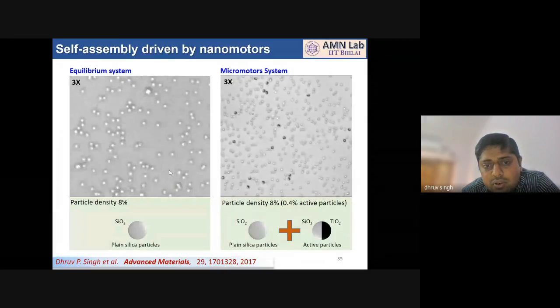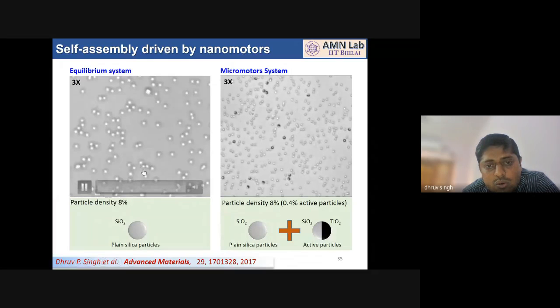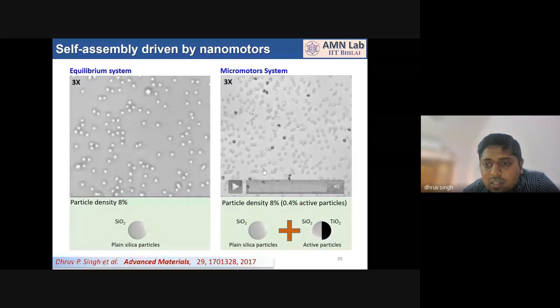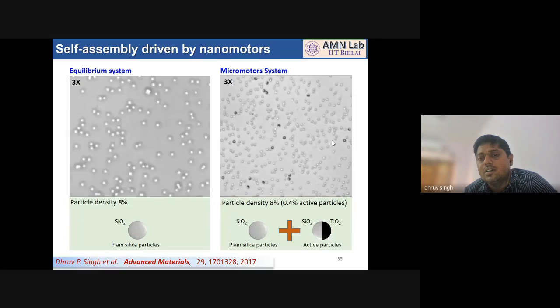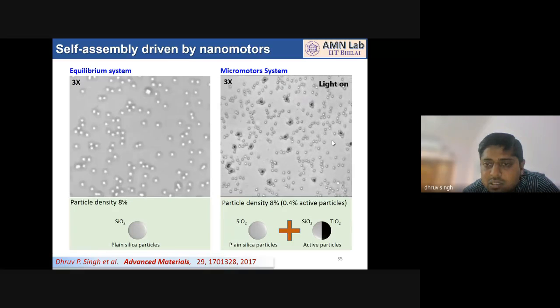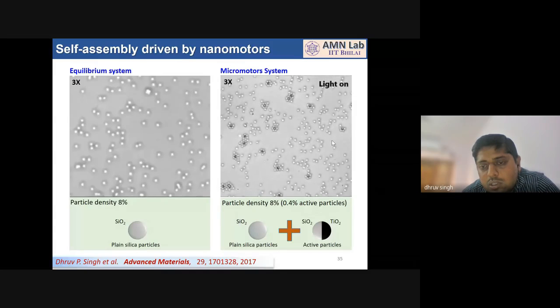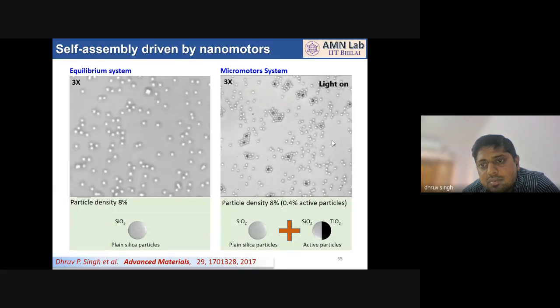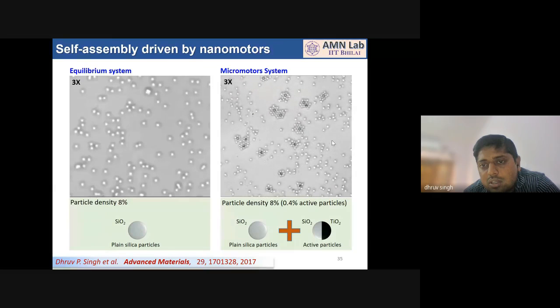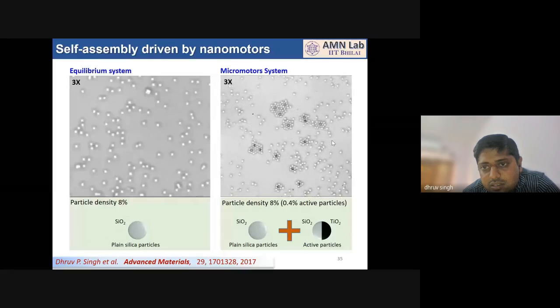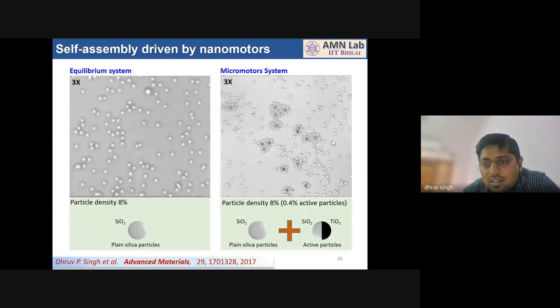And now what happens if I add a small fraction of nanomotors in this colloidal system? So now I am here. Only these black half dots here are the nanomotors, and all the rest, the white particles, are the silica particles or the inert particles. And let's see what happens if we turn the activity on. We see that these motors start to move through the passive particles. They collect them, they crystallize them, they form small crystallites. Crystallites further grow in size by fusion. So they grow in size and they start forming bigger crystals.